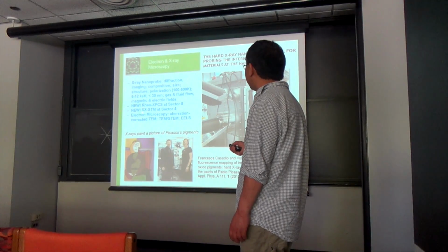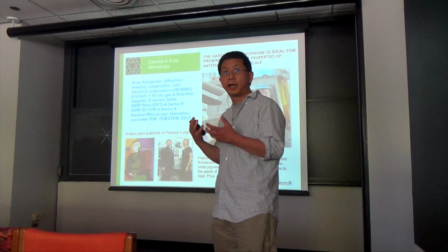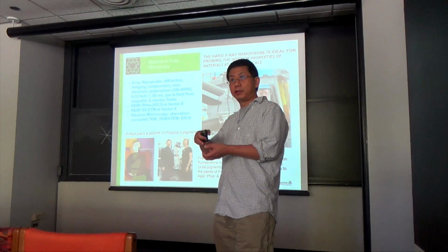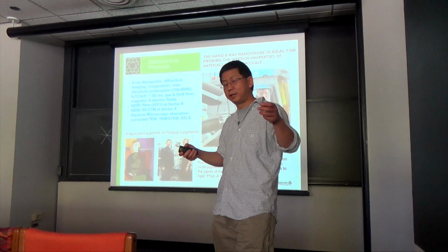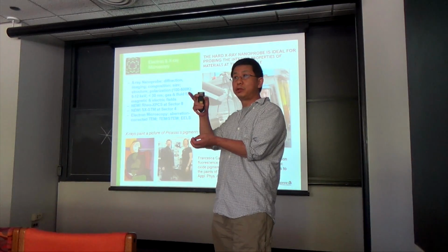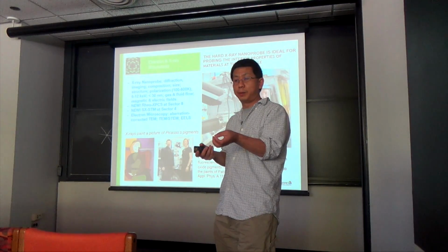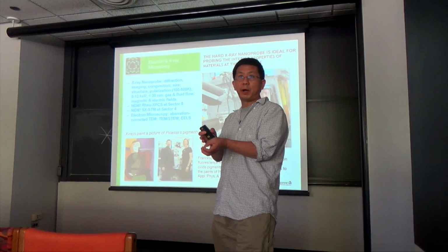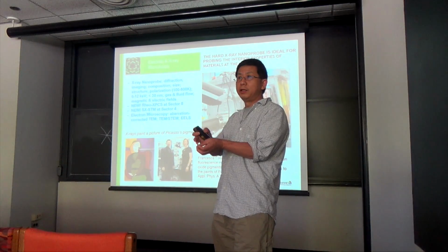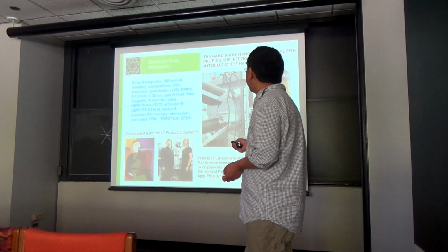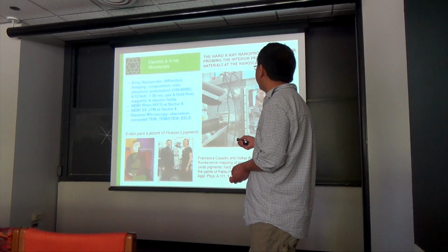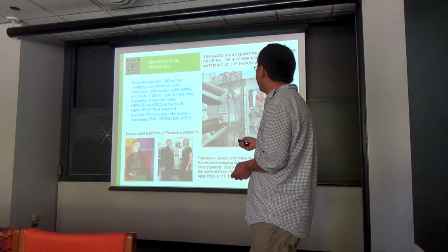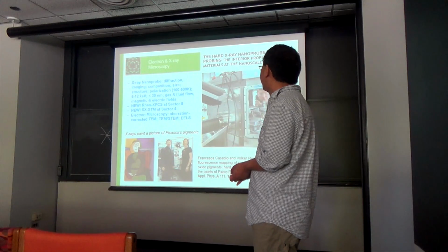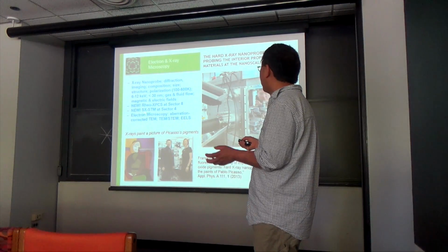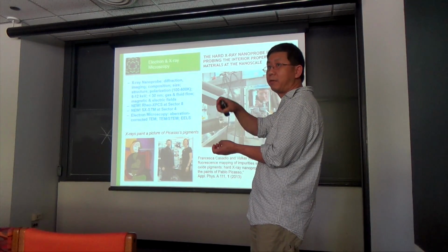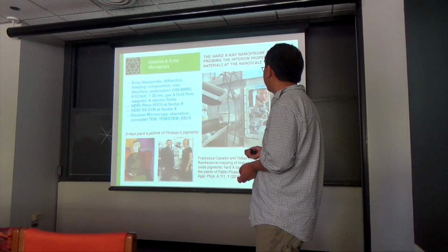And the third technique is called SX-STM. It's a technique that combines X-ray with scanning probe microscopy. Essentially, you take the X-ray and go through the absorption edge of each different element. If you know X-ray spectroscopy, you will know that if you tune the energy of the X-ray through the absorption edge, then essentially you have a large absorption, right? So you change the electronic absorption edge of that element. What happens is that locally the STM is acting as an antenna to pick up the signals from the sample. So they can actually have chemical specificity locally, what kind of elements, even single atom elements, correspond to that specific area.